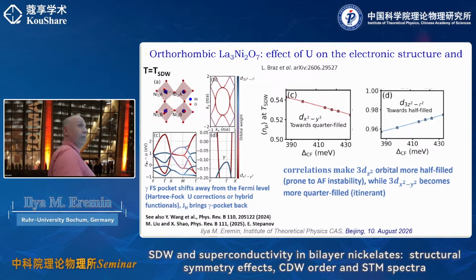In fact, you can just take a DFT, or the tight-binding model that you derive from DFT, which contains this gamma pocket, and put it in a Hubbard-Hund model, and then just do a Hartree-Fock calculation, looking only into the band renormalization due to static U. And you get exactly the same. You see that once you have a non-zero U, it immediately shifts the position of the gamma pocket below the Fermi level. And you try to understand what the origin of this is. You can also play with the crystal field splitting and with the U. Here the results are presented with a crystal field splitting.